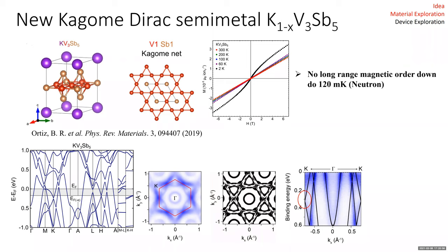I see. And one related question is, when it's doped away from stoichiometric ratio, one minus x, is there any evidence of the Kagome lattice being distorted, say to a breathing Kagome or anything like that, that might explain that you have a net magnetic moment? Yeah, very good point. Very interesting question. At the moment, there is not. Our collaborators did neutron scattering down to quite low temperature, below, of course, where we measured the anomalous Hall effect, which was an order of magnitude larger in temperature than this. And they don't see evidence of distortion.